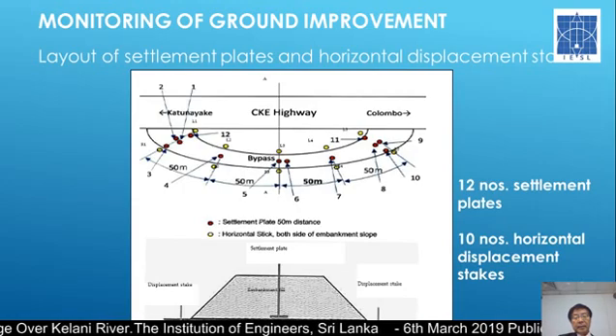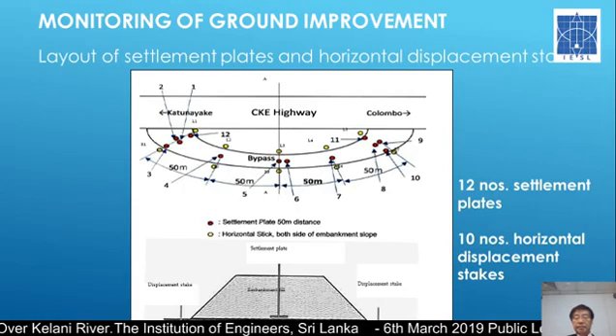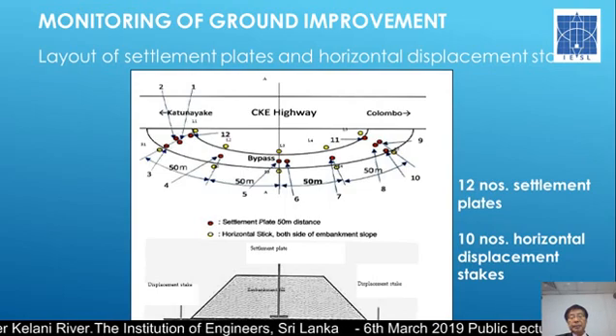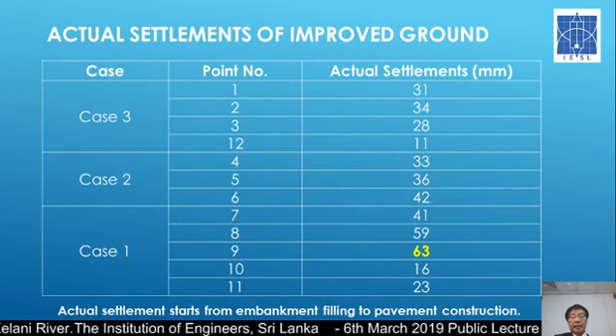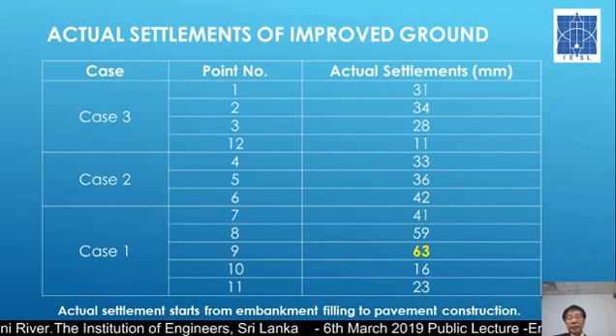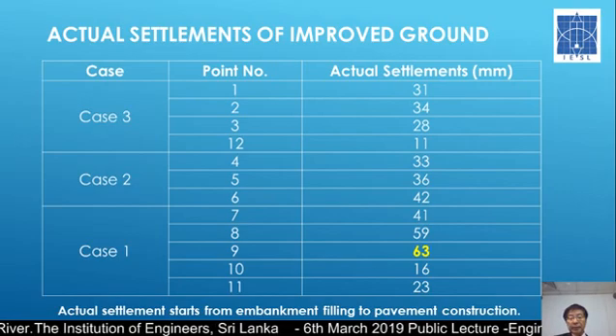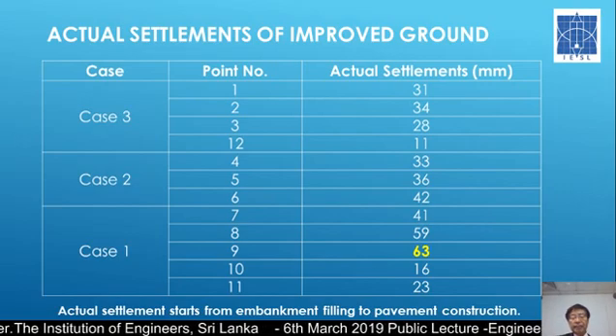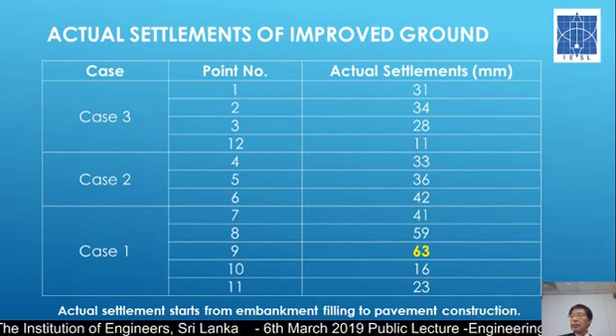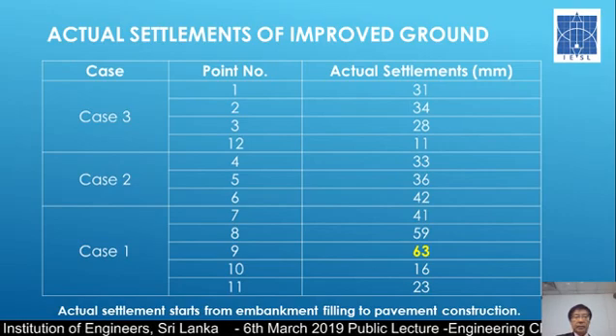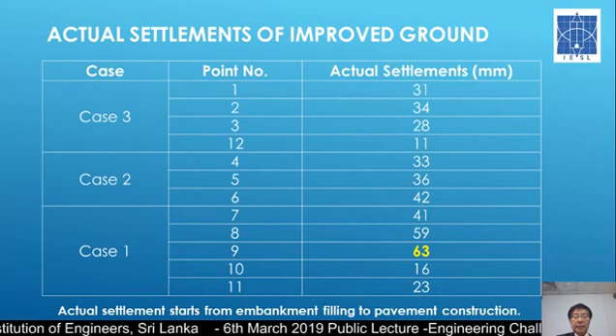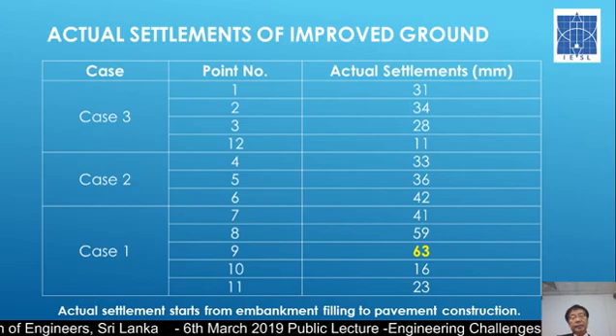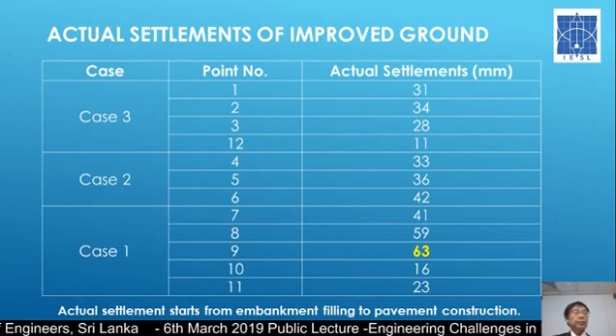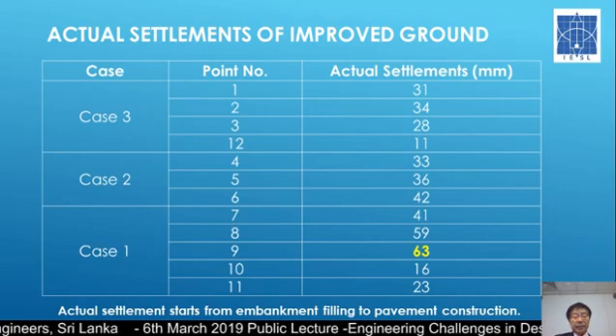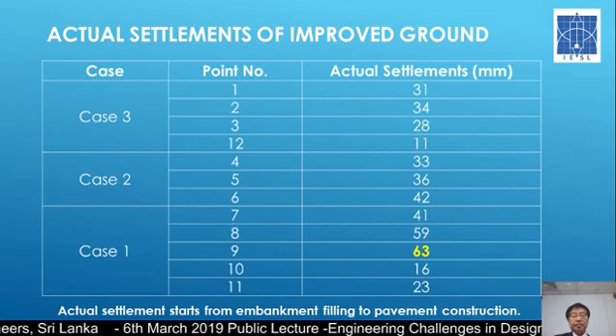Monitoring was done at 12 points for the settlements, and horizontal displacement was also measured. And the actual settlement from the start of the embankment until the end of the pavement is merely 63 millimeters, which is much smaller than the expectations. And this bypass is already open to traffic, and there has been no settlement since that opening.